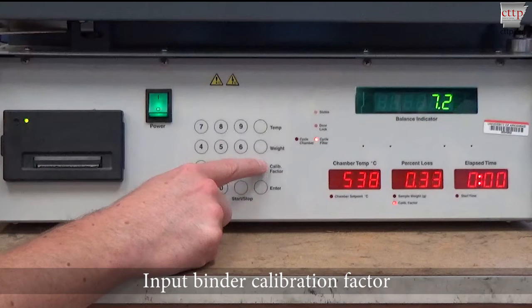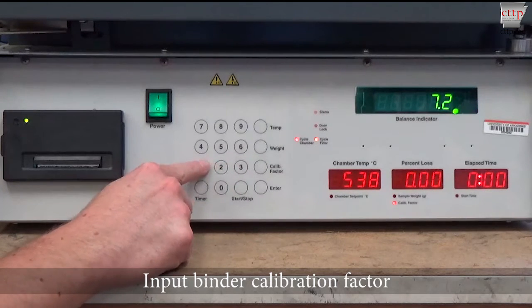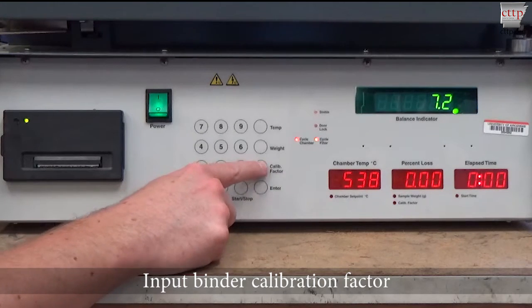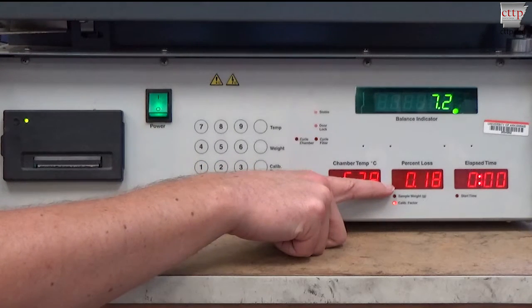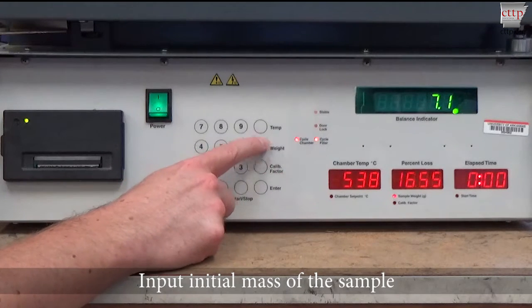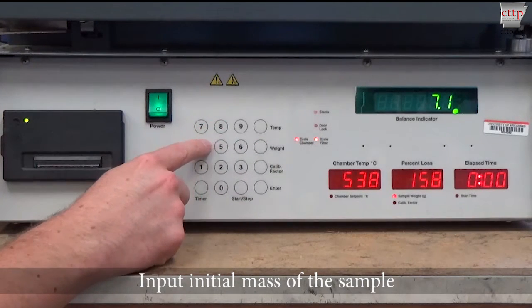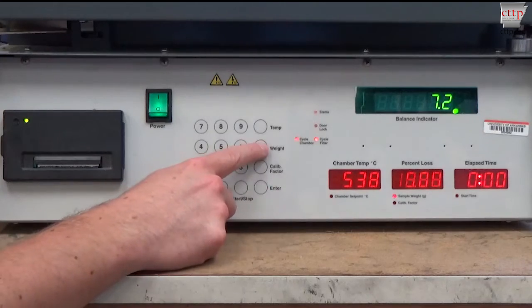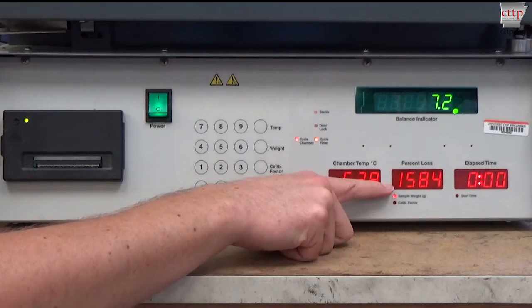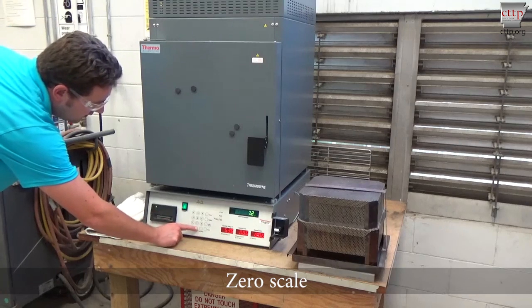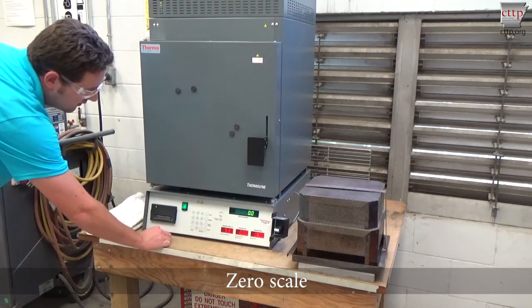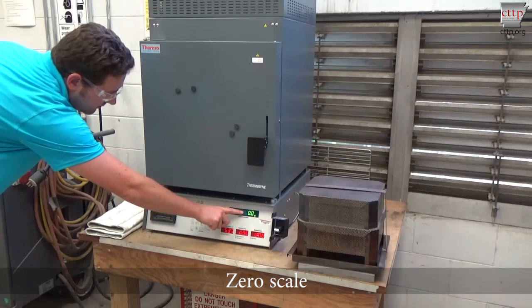Input the binder calibration factor by pressing the Calib Factor button and then quickly entering the value and pressing Enter. The decimal is automatic, so a value of 0.18 would be entered as 018. Verify the entry by pressing the Calib Factor button again. Input the initial mass of the sample by pressing the Weight button, entering the initial mass, and pressing Enter. Verify the initial mass by pressing the Weight button again. Zero the ignition oven's internal scale by pressing the Zero button. Verify that the scale reads 0.0.